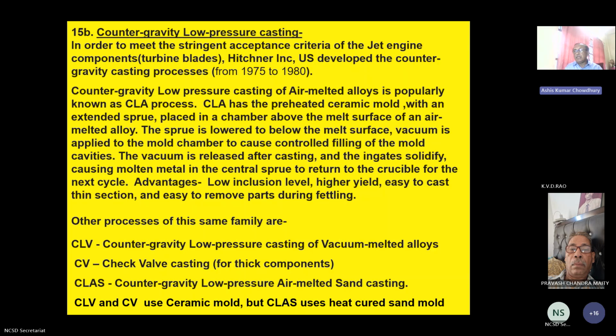CLA has the preheated ceramic mold with an extended sprue placed in a chamber above the melt of an air melted alloy. The sprue is lowered to below the melt surface. Vacuum is applied to the mold chamber to cause the controlled filling, anti-gravity filling basically, of the mold cavities. Vacuum is released after the casting and the ingate solidify, causing the molten metal in the central sprue to return to the crucible of the furnace for the next cycle.